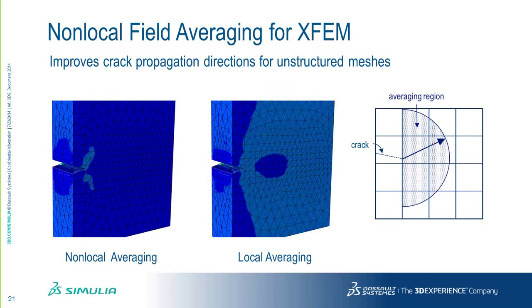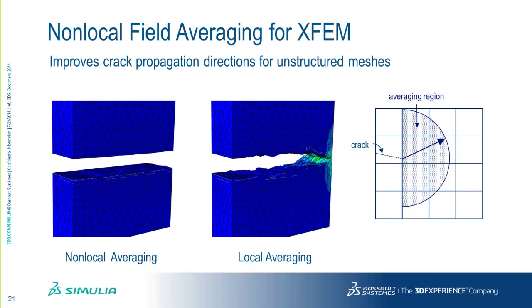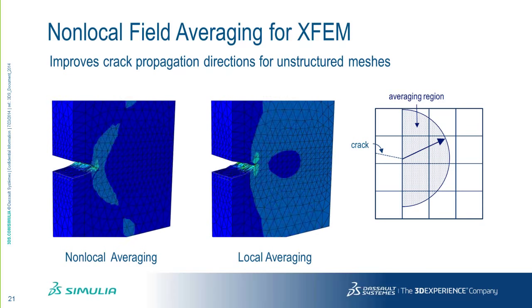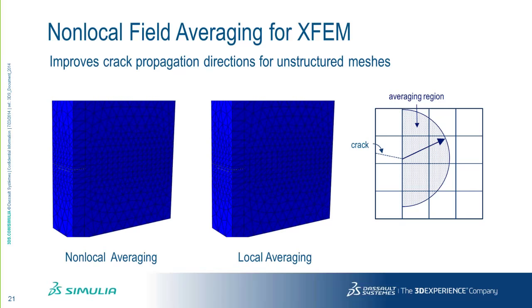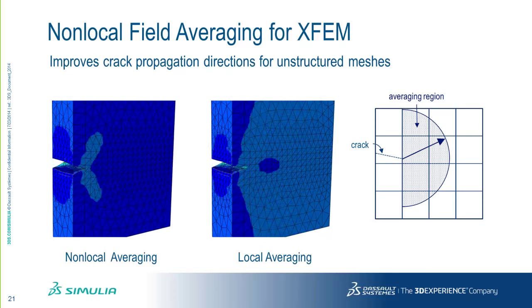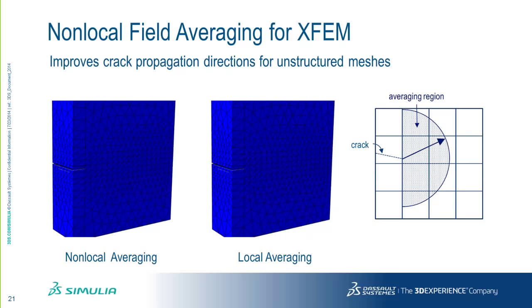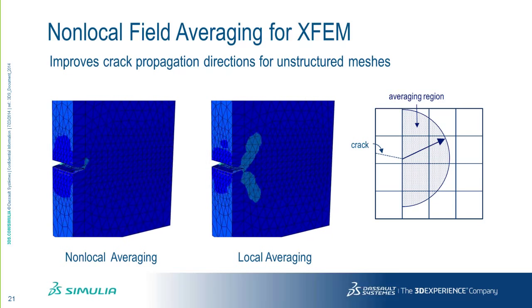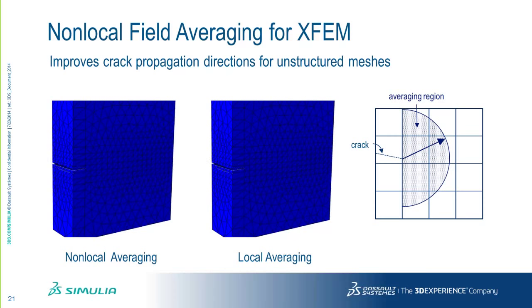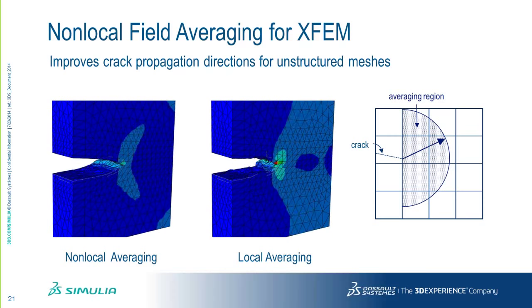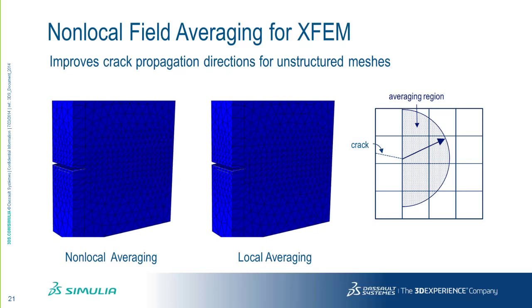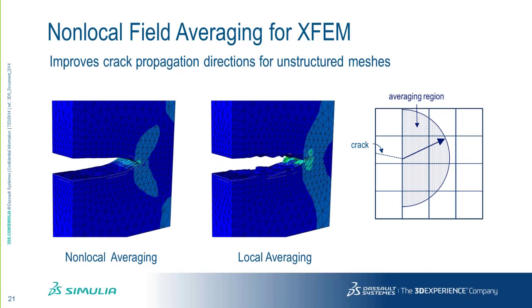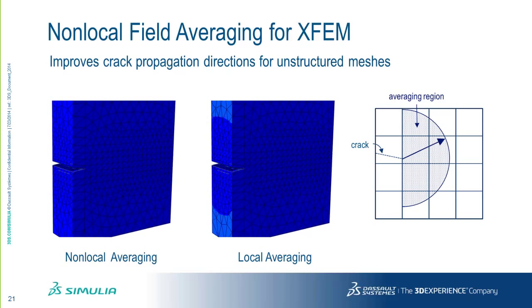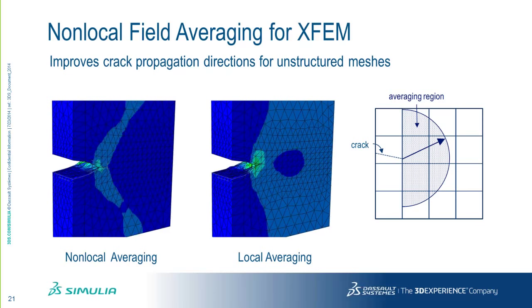Another enhancement for XFEM is work done to try to improve the crack propagation direction calculations for unstructured TET meshes. The idea here is that when we're trying to compute the fracture direction, we need to look at the stress field ahead of the crack tip. And for unstructured TET meshes, as you might know, the stress field can actually be somewhat noisy. This is just a fundamental feature of these first-order TET elements. And the effect of that noise can be some slight inaccuracies in our propagation direction.